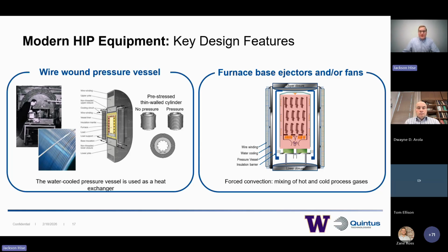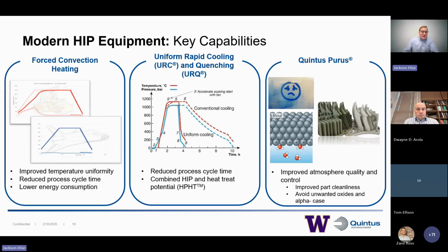We also at Quintus here have forced convection, which uses fans and ejectors at the base of the vessel to circulate gas flow within the system. This leads to the mixing of hot and cold gases, leading to temperature uniformity and temperature control. Really, the value of these two equipment features is first forced convection heating.